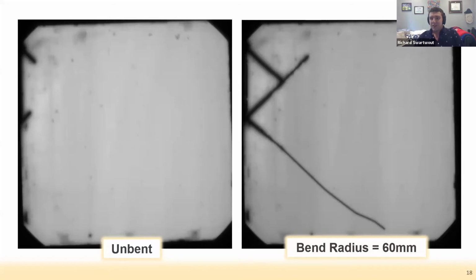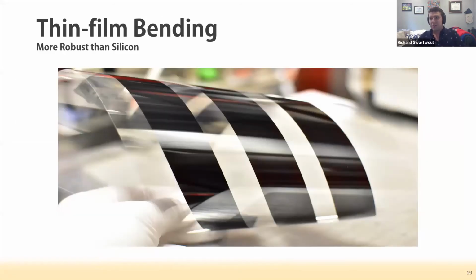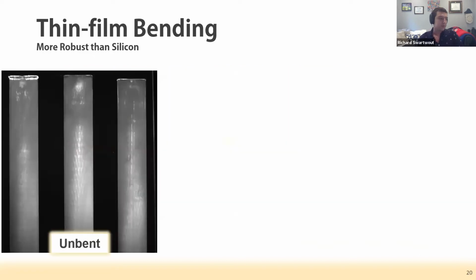Thin films, on the other hand, we can print them on very flexible plastics. This is an image I'll talk more about later, but perovskites in general don't have this fundamental limitation. If we look at printed cells underneath the same photoluminescence inspection system, an unbent film looks a bit like this.